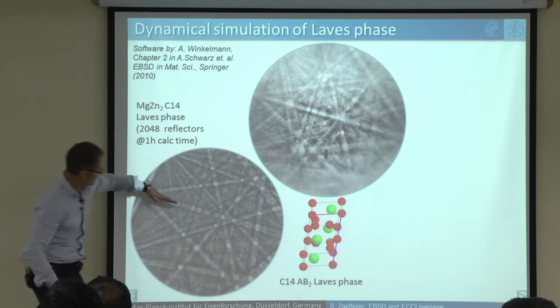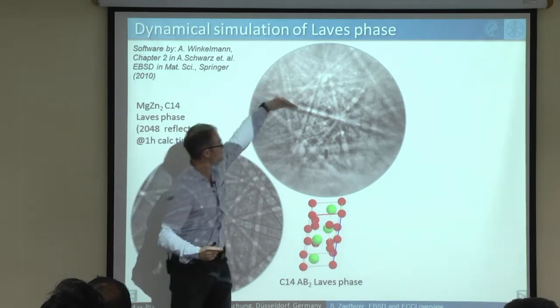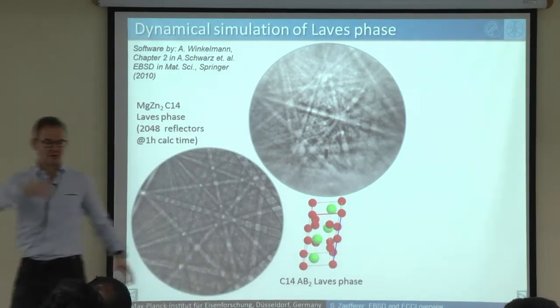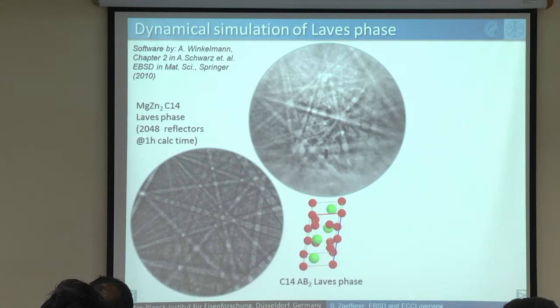The lines here are all at the correct place with respect to this one. But if you are now looking for a while, you say, but this does not look as if it fits. Yeah? For example, here, this center line should be white in the center and have then a bright diffuse band, but it's not white, and it has black sharp bands. And many other places I could show you in this pattern where it doesn't fit. So you think, this software is not good, not to say anything worse than that.